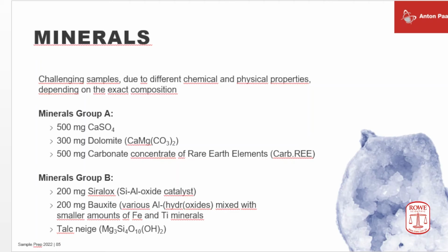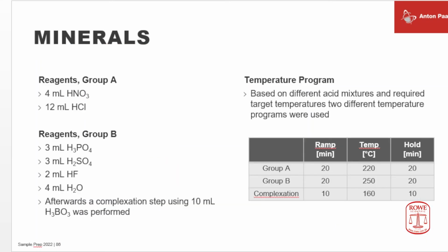Group A, like I said, aqua regia digest. Group B, the classical 4-acid digest. Maybe not the classical, but here some water was added. Why did we add water? In order to get a better solubility of the large amount of material. Also the temperature profiles, group A only took 220 degrees, 20 minutes ramp, 20 minutes hold time, whereas group B was taken to 250 for complete destruction. But again, within less than 1 hour, you can decompose 20 samples.